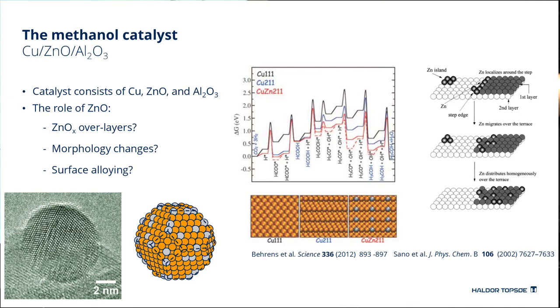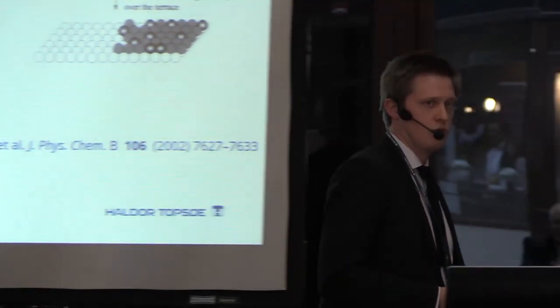There's a theoretical study where you can go from CO2 and hydrogen to methanol here. And if you have pure copper, it's following the black route here. And if you have a copper and zinc surface alloy, you will follow the red route here. So you can really see that putting zinc in the surface lowers the energy barrier from going from CO2 to methanol.